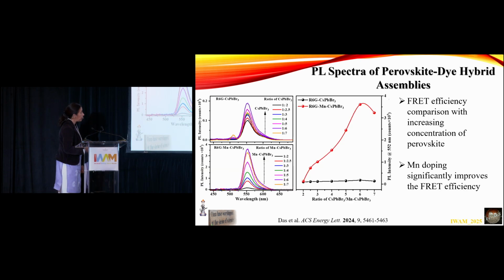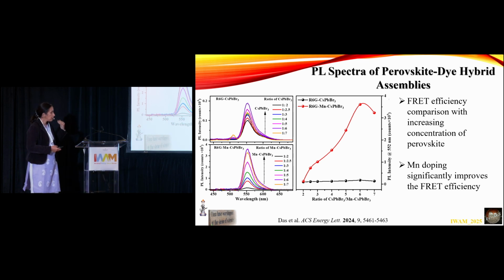So this is even better seen here when you change the ratios of the cesium lead bromide to that of the dye. Instead of titrating with the dye, why not titrate with the bromide? So we see that it just keeps increasing. You keep adding more and more cesium lead bromide. Normally in most systems, because of self-absorption, it kills itself. But in this case, the self-absorption is significantly reduced and the FRET efficiency is increased.